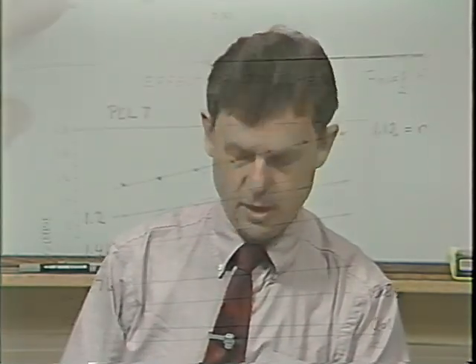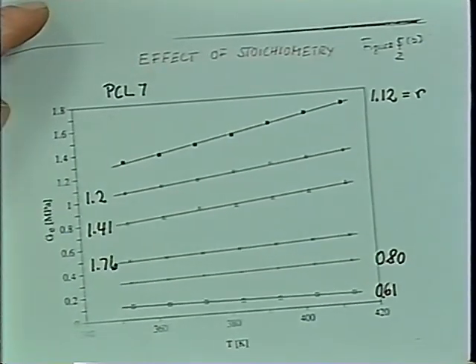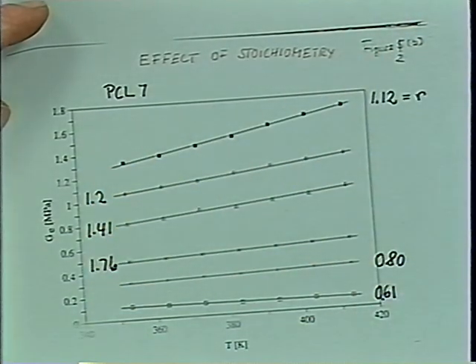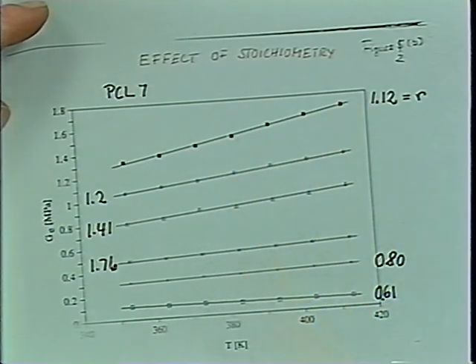And you can also see that for a set of samples which were cross-linked at different stoichiometry, this effect of stoichiometry. And again, as the modulus goes up, you see a bigger temperature dependence coming in. And here you have close to balanced stoichiometry, you have the highest modulus. Then on either side, if you have a lower amount of crosslinker or a higher amount of crosslinker, you get lower moduli. And all of this is very consistent. In fact, we used those shift factors and shifted data near the gel point and the gel behavior was described by that very nicely.